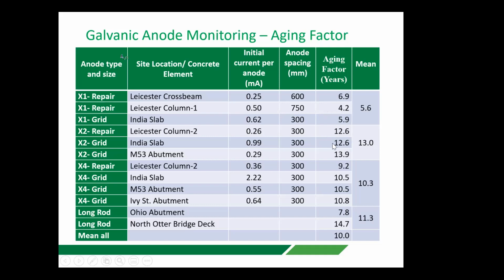You could see that we were able to improve that considerably up to about 14 years, simply by reducing the spacing of the anodes. We were now asking the anodes not to work as hard, even though these anodes were double the surface area of these anodes. We maintained the current output about the same. Therefore, they were asked to work less hard at the beginning, with the result of achieving a better aging factor.